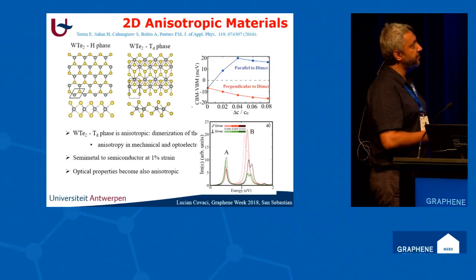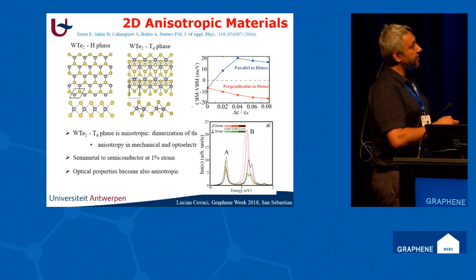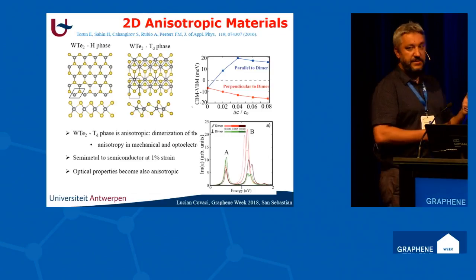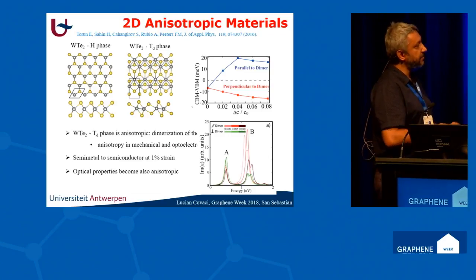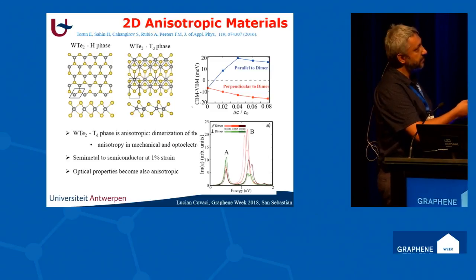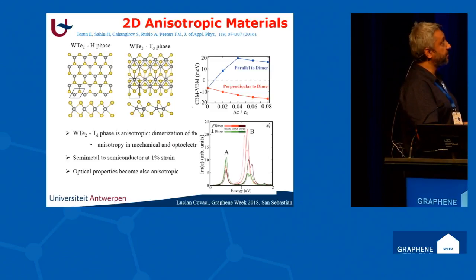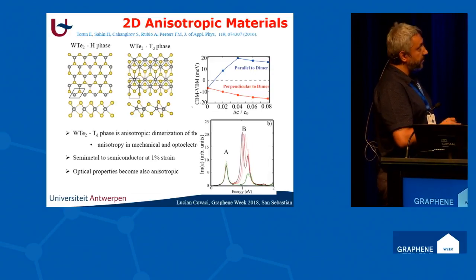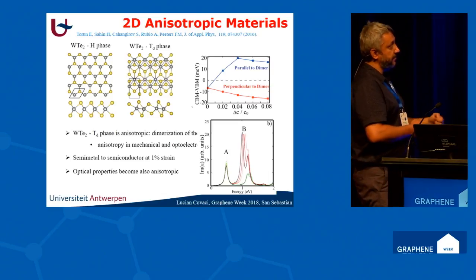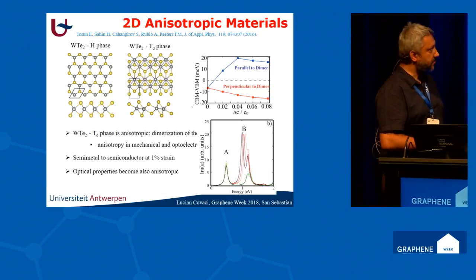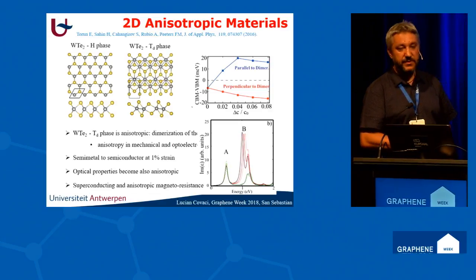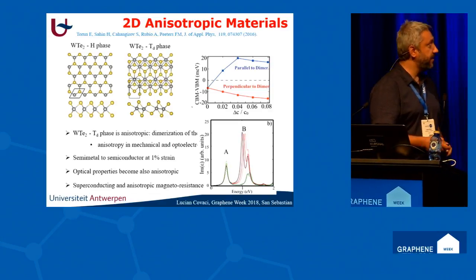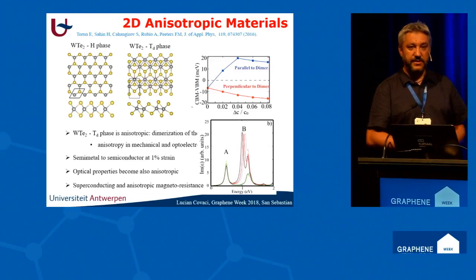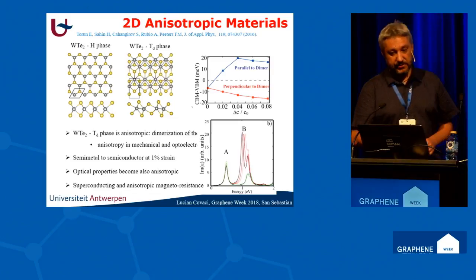So here I just show the imaginary part of the dielectric function, which is shown as a function of the amount of strain and the direction of the response. So there is some anisotropy in the direction of the response, but also in the type of strain. For example, here these results are shown for strain perpendicular to the dimer, while these are shown for strain which is parallel to the dimer. So this material has also been shown to be a superconductor and has anisotropic magnetoresistance, so therefore it should be a very interesting material for applications.